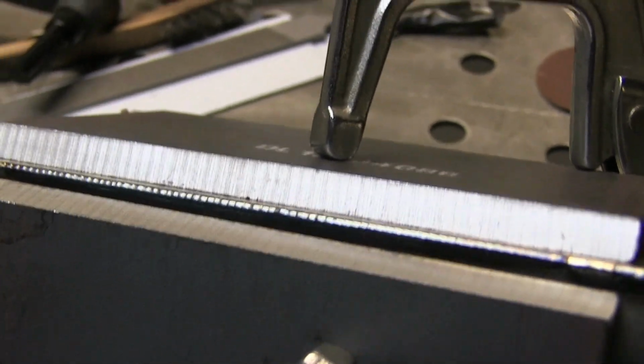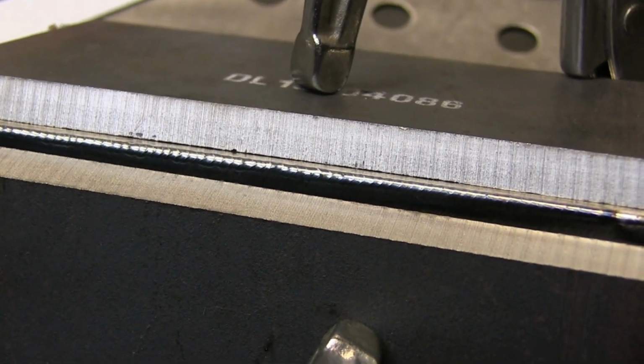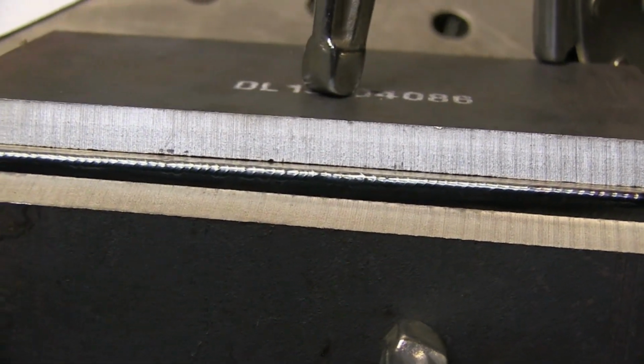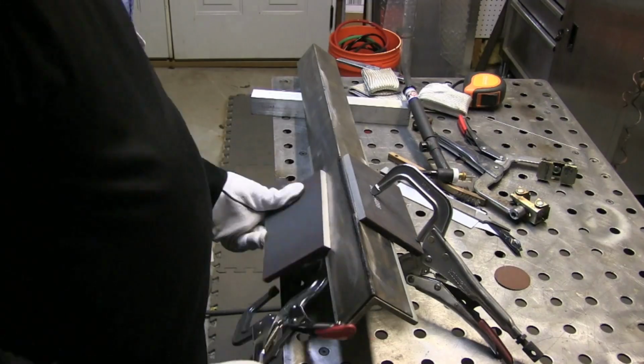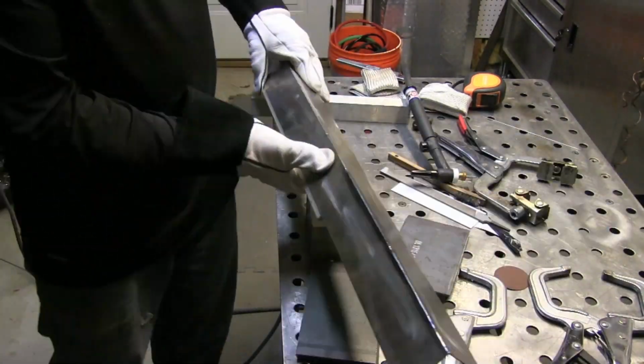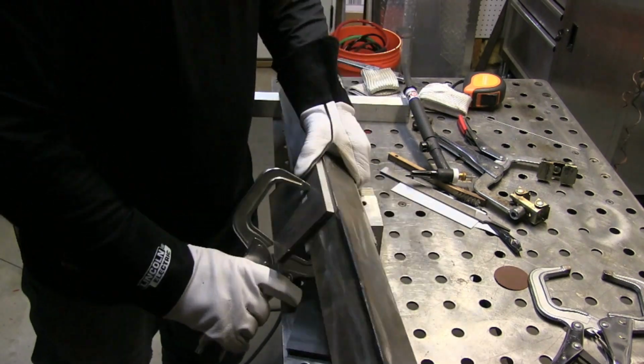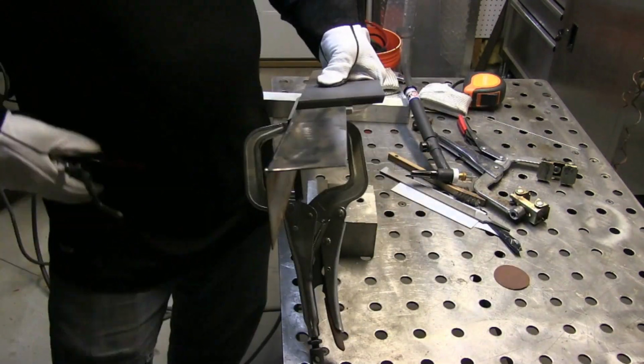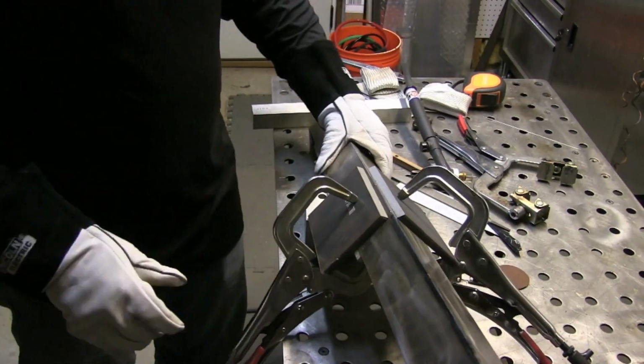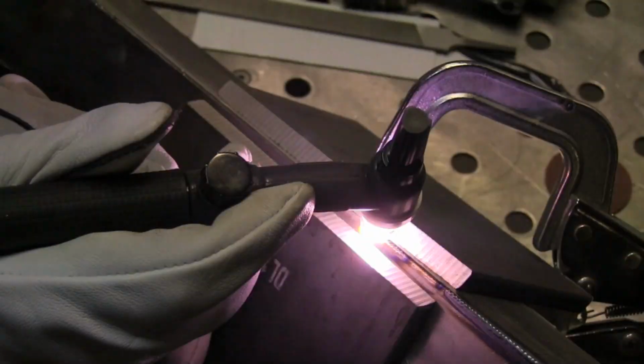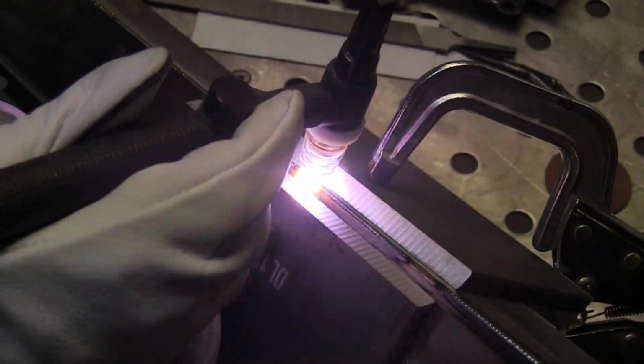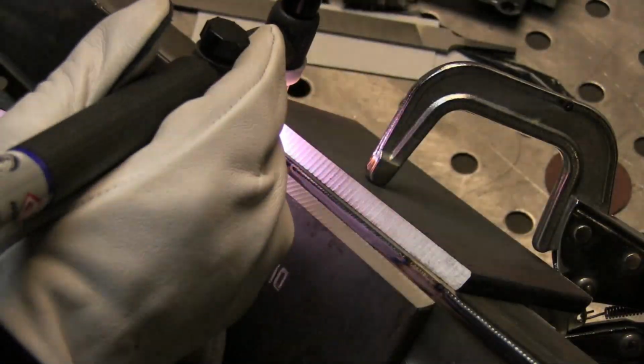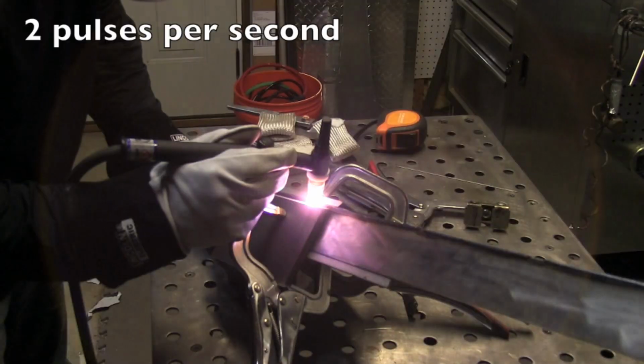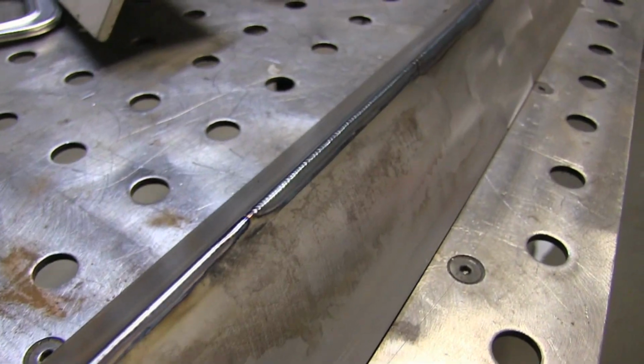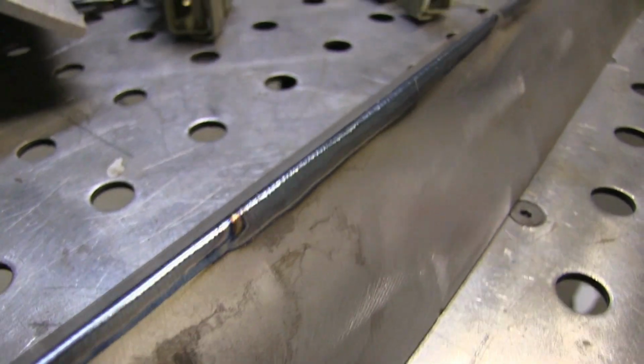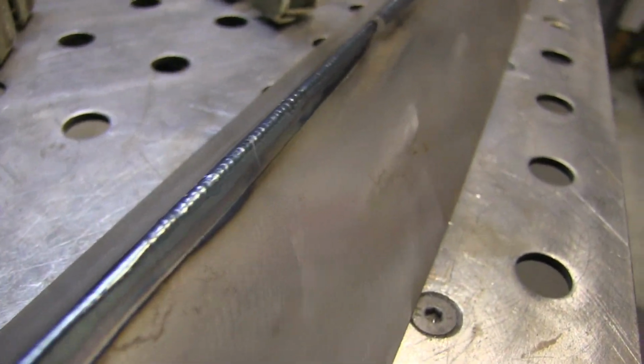And I'm using, again, these 7-inch long pieces. You could go longer than that, but you would probably need two clamps instead of one. But even so, for the few seconds it takes me each time I run those 7 inches, it's well worth the effort to prevent distortion. I even stepped it up to 2 pulses a second, to speed up travel speed. That worked pretty well too. And so there's very minimal distortion in this piece.